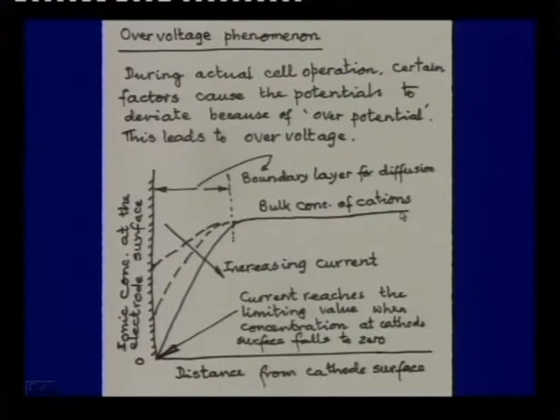either because of a concentration overpotential, because when the current flows, the bulk cations are flowing towards the cathode. The flow has to be because of a concentration gradient. This gradient becomes steeper when the current increases, because there is more flow of the cations, which means you have a steeper gradient, that is why a greater flow, but there is a limit beyond which we cannot push it further, and that becomes rate controlling. So, because of this concentration gradient, there is a concentration overpotential, and then a limiting current, or for a given area of the electrode, a limiting current density, which limits the amount of metal you can deposit on a cathode in a given cell.